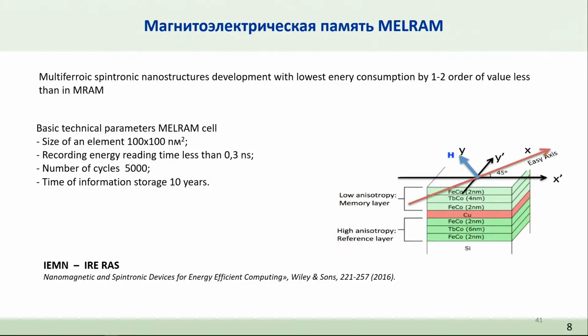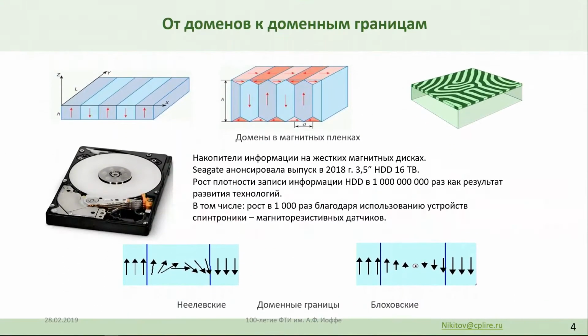We can also note that magnetic materials, in the antiferromagnetic or ferromagnetic case, without magnetic fields are divided into so-called domains. The size of the domains, depending on the thickness of the film, can be very small. So the domain wall between two domains having different directions can be a few nanometers in size. And this domain wall can be managed by an external magnetic field or by light, for example, because it also has a magnetic component.